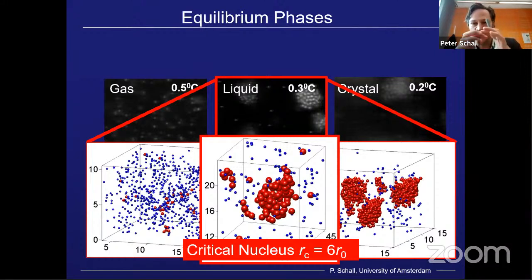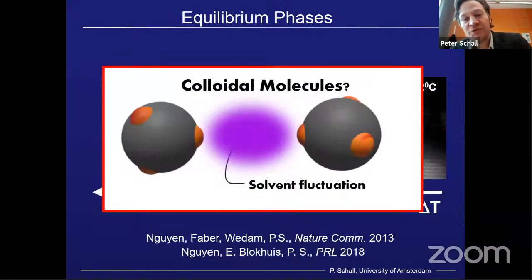However, if you have a droplet that is curved, at the atomic scale, you have slightly fewer nearest neighbors because of the curvature, and then the interface tension changes. But it's not clear by how much, so we could measure that nicely in this model system. Anyways, this is one example. What I want to get to is whether we can make more complex structures.